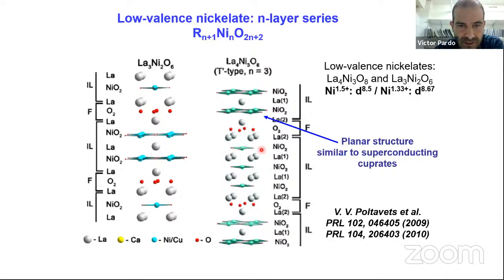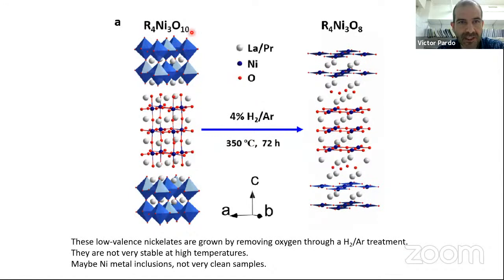So they share this structural motif, these nickel O2 planes, square lattice, similar to that of the cuprates, but they appear in bunches like this. n equals 3 has 1, 2, 3 layers here, which is separated from the other 3 by a fluorite slab. And in the n equals 2, you have 2 layers here of nickel O2 that is separated by this fluorite slab from the other 2. So these are interesting, certainly very similar to the cuprates, and with a feeling that is getting close to the interesting part of the phase diagram of the cuprates. So they produce them in this way.